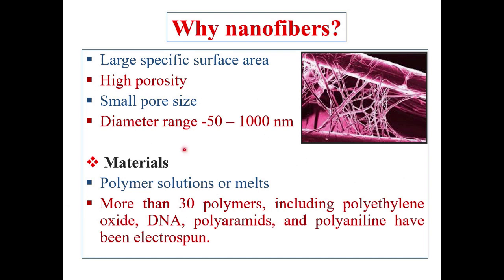Why nanofibers? When we talk about fibers, fiber strength is very high. There are many fibers available, synthetic fibers and natural fibers, as I mentioned earlier. Nanofibers have a large specific surface area. The surface to volume ratio is very high as compared to normal nanomaterials. Porosity is very high, highly porous, because fibers are woven like this, therefore high porosity. The pore size is also small, specifically the diameter is in the range of 50 to 1,000 nanometers.